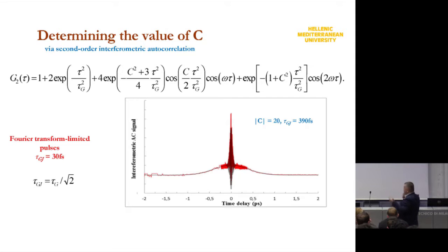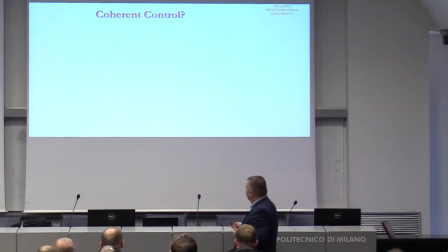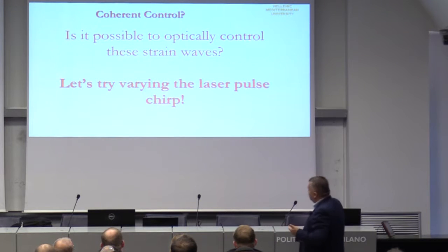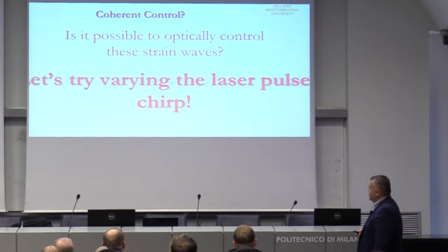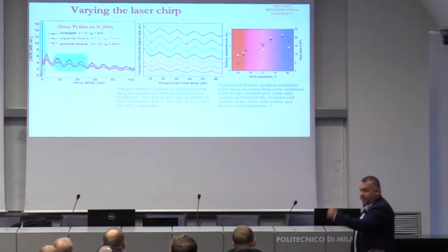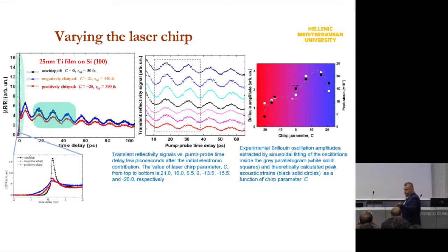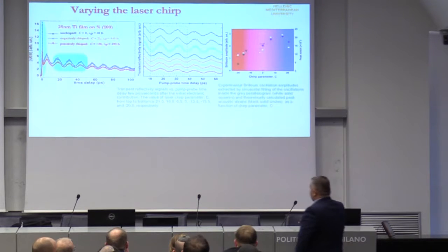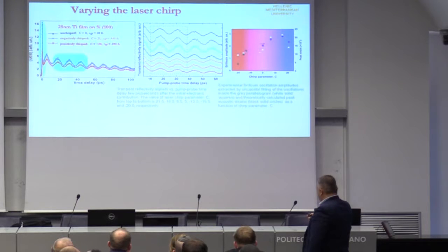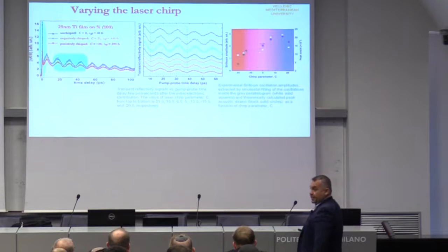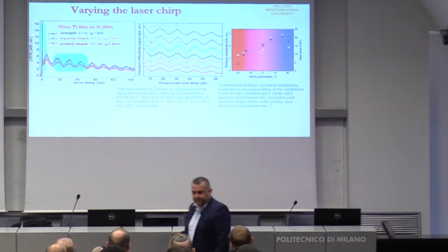We can actually measure the chirp by different techniques. Is it possible to optically control? Let's vary the laser chirp. So, here are the results. Titanium on silicon now, same material. We try to play with the chirp. What do we observe? Here are the oscillations at different chirps. You see blue is the negative chirp, red is the positive chirp, and black is the Fourier limited pulse.